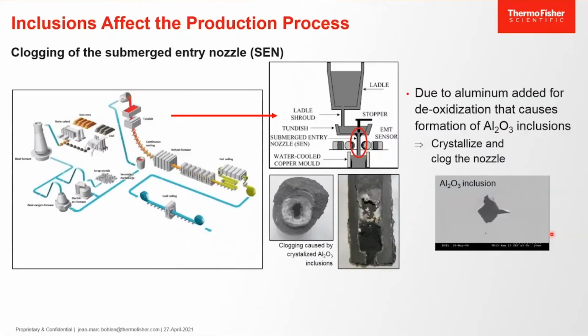I said that inclusion also affects the process. This is a famous example. Actually, a very common issue for the steel makers. Clogging of the submerged entry nozzle is taking place when aluminum is added for the deoxidation of the steel. This causes the formation of aluminum oxide inclusions that crystallize and clog the nozzle.